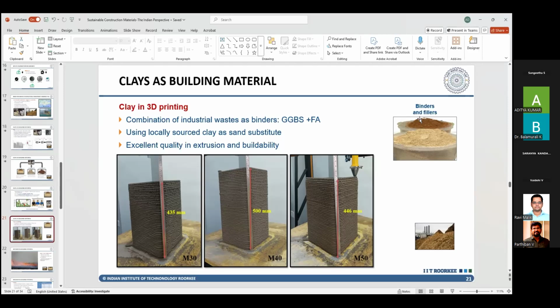So clay, the understanding around clay, the clay's availability globally, and economic wise also. So if you try to produce, we are still yet to break even. But if you're producing cement using metakaolin, or let's say the cement that I talked about, limestone calcined clay cement (LC3), it's very close to the cost of normal OPC. So one of the ways that you can see the economics working out in favor of these alternate materials is if you start charging for the carbon credits.